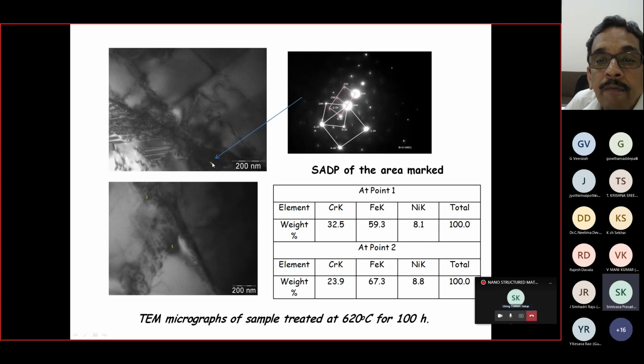So we try to take a diffraction, SADP, a selected area diffraction. I have selected this area. Now, since I am impinging an electron beam, when an electron impinges a material, we get X-rays. So we are trying to take a diffraction pattern, which is giving something like this. Basically it is a dark background with bright spots. Now we index it. That's a small process. It's not very difficult, but it can be understood.